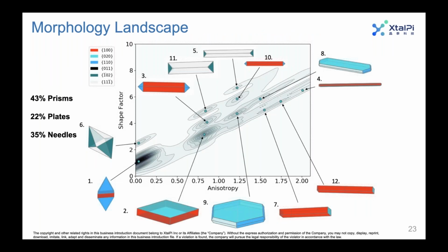We calculated the morphology landscape for metformin HCl, and this is what it looks like. So we see that there are possibilities for prisms, needles, and plates. And then I've put the percentage breakdown. You'll notice some numbers next to some of these morphologies. That gives you an idea of the most probable morphologies based on this morphology landscape. So we see that prism habits are very probable based on their probability density, and then they go down from there. So like this would be the 10th most probable shape that we see up here, or 12th most probable, or 3rd most probable here.